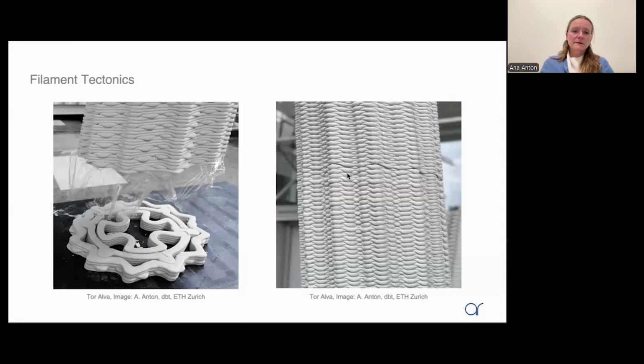Unlike the previous project where we had this concrete precast in between the printed components, we opted for a process that replicates match casting. We 3D printed the last 5 layers of the component that comes on top. We put a thin plastic film between them, and we printed the component that comes on top. In the end, the joint can be very, very clean, almost invisible when you assemble these 2 components together.